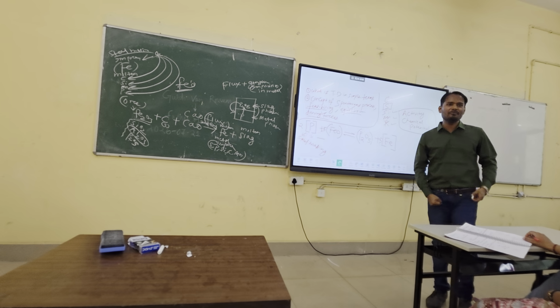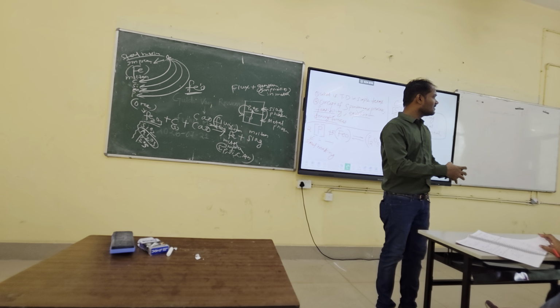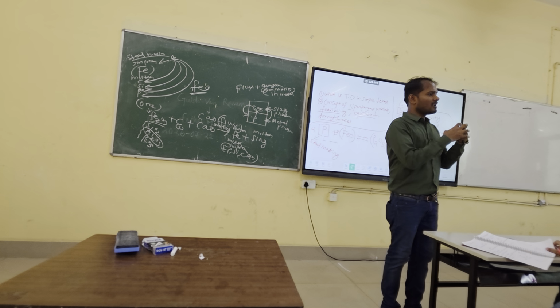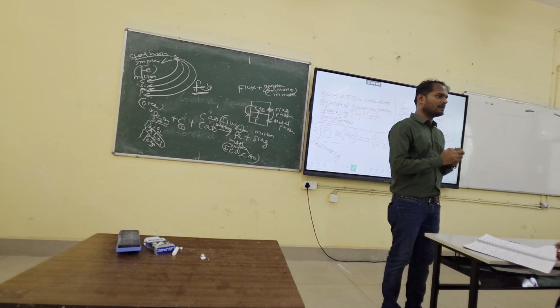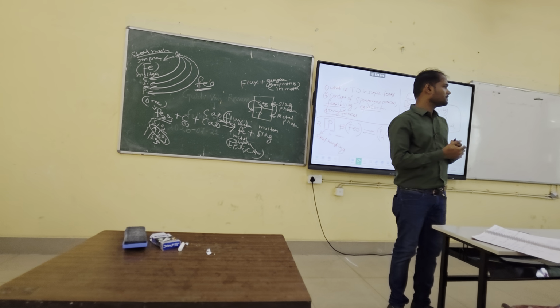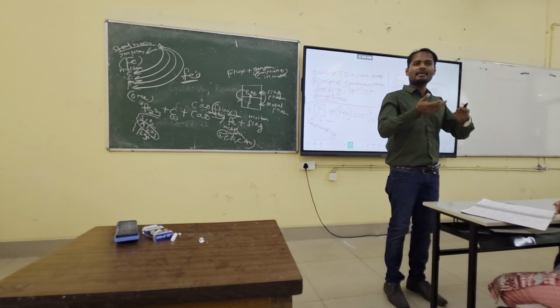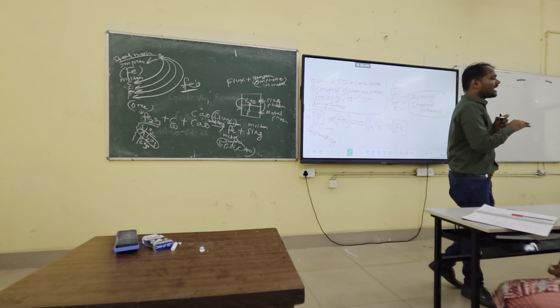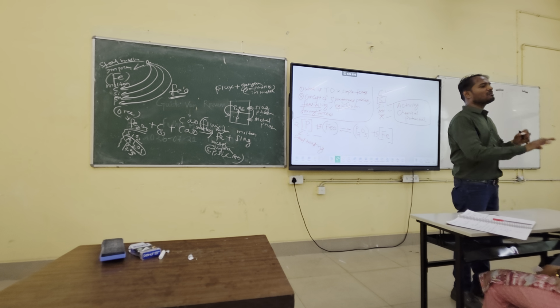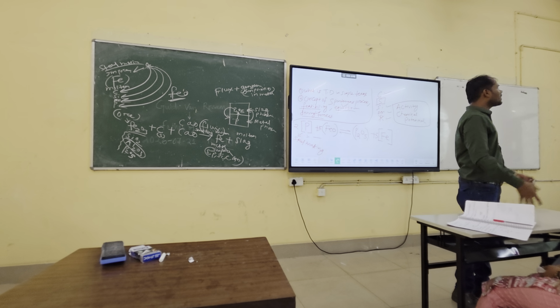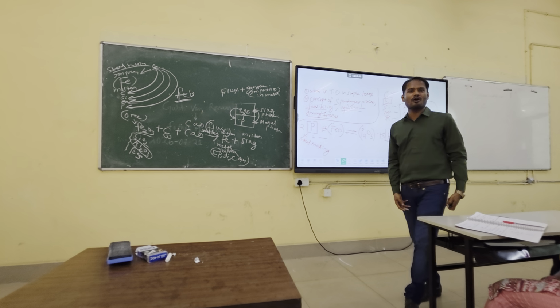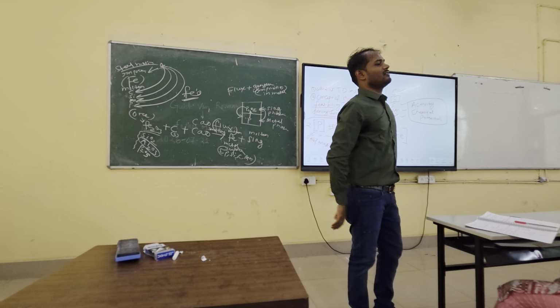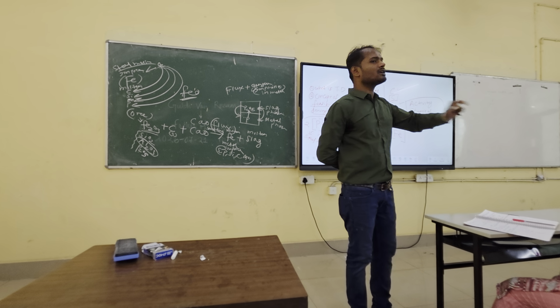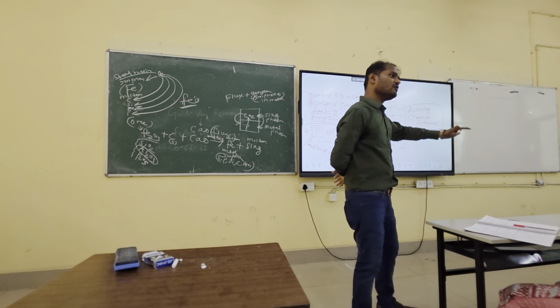So what will happen? The reaction will happen between them, of course, because they are opposite in nature, right? So there will be a strong bond between lime and P2O5. It is called dicalcium phosphate or calcium phosphate. Once it forms dicalcium phosphate or calcium phosphate, the activity of phosphorus will go down in the slag, or the chemical potential will strongly reduce. So what happened? The chemical potential of phosphorus is reduced in the slag now. It cannot come back. It will stay there. But if you do not add any lime, phosphorus will go as P2O5 into the slag. Again, it can be reduced by carbon or by some other metals to become phosphorus and come back.